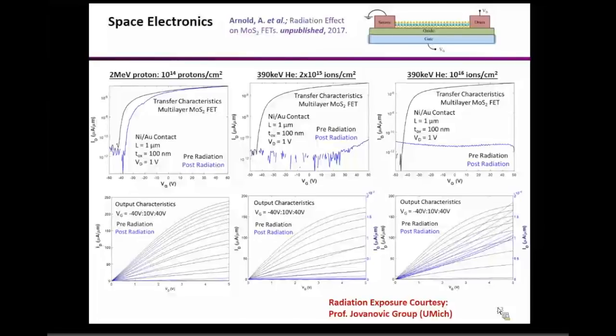This is actually a typical dose that a satellite will accumulate over 1 year. 10^14 protons is a typical dose. But we are also a little bit ambitious. We also tried heavy ions like helium with very, very high fluences. And of course, at that stage, things start to degrade. But our initial assumption is it's probably not the 2D material. It's mostly the oxide that is getting damaged, and that's why we're not getting any kind of gating action from these devices. But again, this result points to the idea that this 2D material can be implemented for harsh environments like this space application.